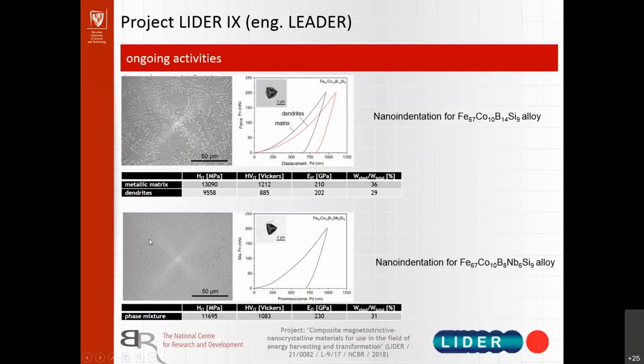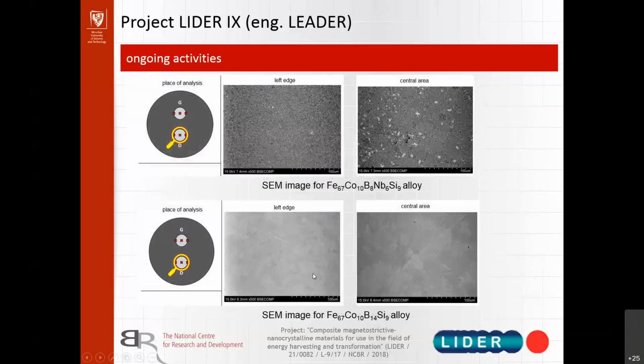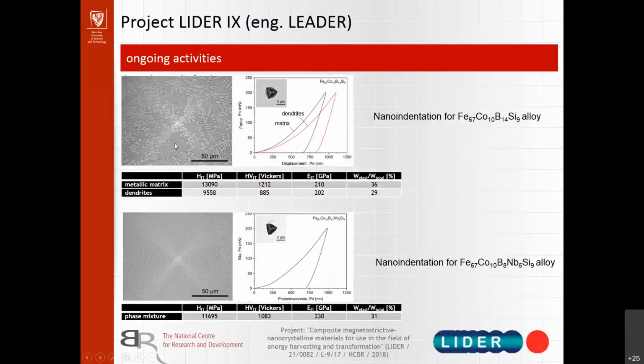We can see that the 5-element material is still crystalline, but we can also very clearly see that our 4-element material from the previous slide, the one from the top, seems to be also crystalline, however with some dendrites. But these dendrites are, let's say, soaked in metallic matrices. With this method, we were able to obtain the instrumental elastic modulus for those two materials.